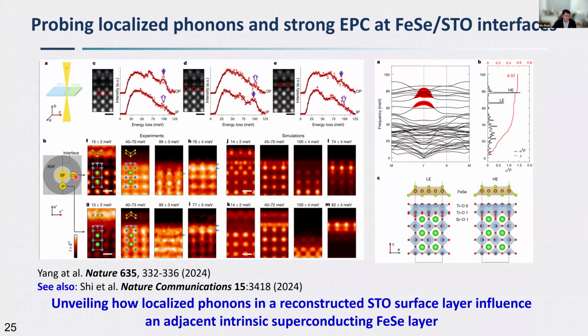So using vibrational EELS, and probing with momentum selection, either perpendicular to the interface or parallel to the interface, they can see localized phonon modes that are just localized at the interface, and this is also reproduced by the calculation. So these two studies show that localized phonon modes emerge at this reconstructed interface of STO and influence the superconductivity transition in the iron selenide layer.